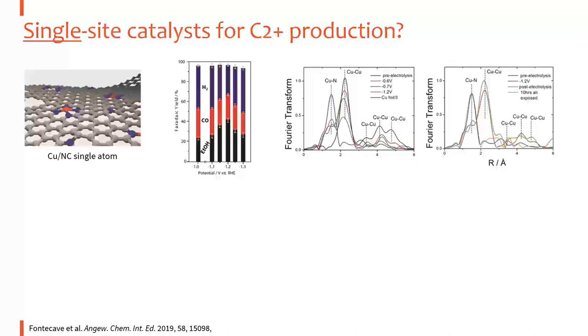And what is kind of like magic is that when they took the catalyst out of the CO2 reaction and exposed it to air for 10 hours, they found that the copper-copper bond disappeared while the copper-nitrogen bond reappeared. So they think there are some reasons for the process to reverse back to single atoms after reaction. That means if we really want to understand the catalytic site, we need to examine the reaction under operating conditions so that we can get the real information for the catalysis, not only characterize the post-electrolysis samples, because that will give us misleading information.